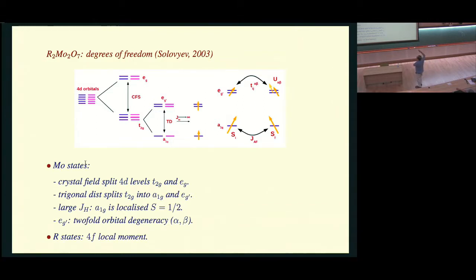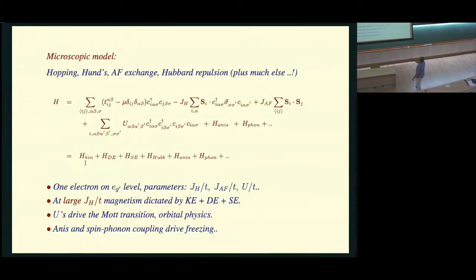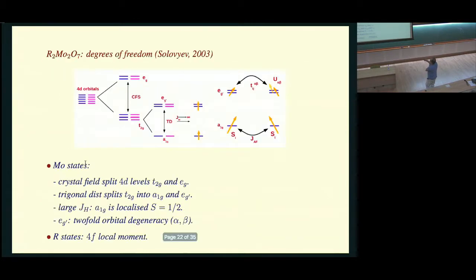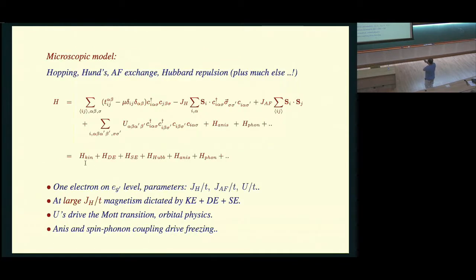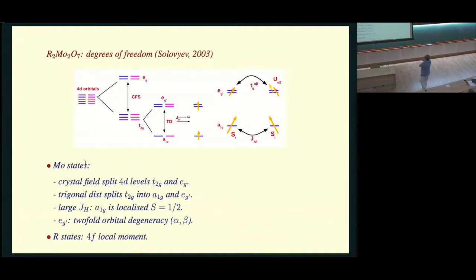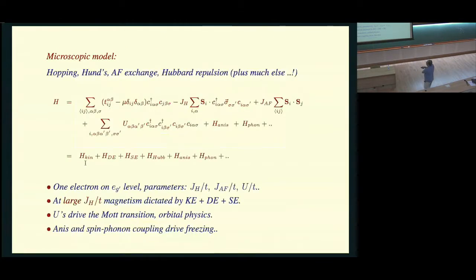So I would have to write a model which has this S degrees of freedom in the background, not to be confused with the M's which come from the Hubbard-Stratonovich, and a twofold degenerate alpha beta level sitting up there. So the description is very messy, looks like a two-band, two-orbital kinetic energy. It has a Hund's coupling between the A1G and the EG electron. It has an antiferro coupling between two local moments on neighboring sites, and it has the usual Hubbard terms in it.